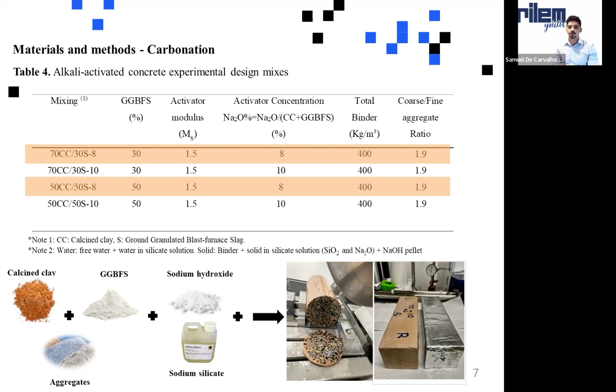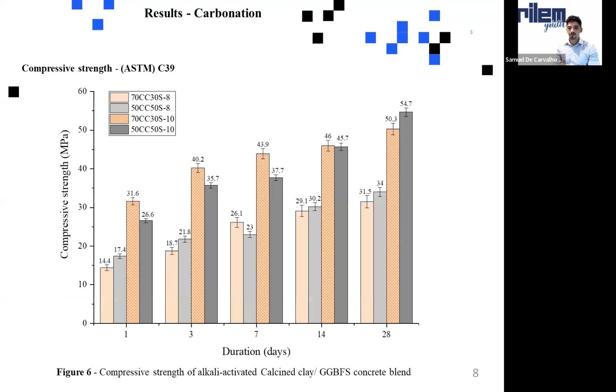It's a commercial calcined clay. You import them from France. So when you blend it with GGBFS, sodium hydroxide, and sodium silicate, that's the mix design, and here's one of the samples of the blend, with also the sample for the shrinkage test. So here is the compressive strength for the carbonation test.